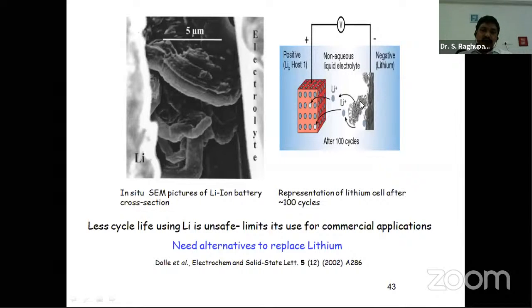And because we keep an entire lithium-ion battery in a closed volume, because it has to be isolated from our environment, we keep it sealed. Whenever you open a lithium-ion battery and see it, it's completely sealed. If you keep lithium in it and it keeps coming out and bulging, its volume increases and it leads to accidents. Because of that, lithium is highly unsafe to use for commercial applications. So we have to find alternative materials for the lithium-ion battery.